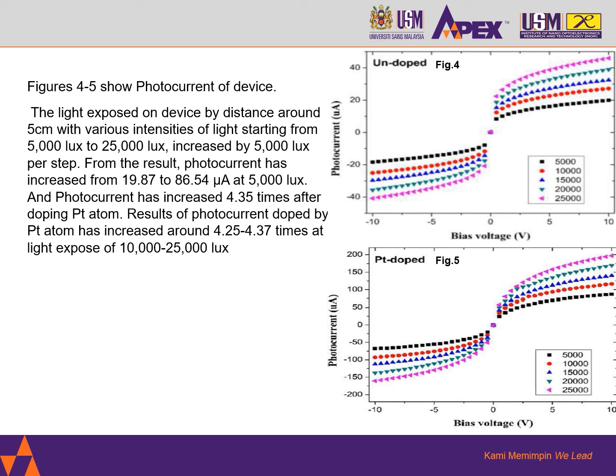The light exposed on device by distance around 5 cm with various intensities of light starting from 5,000 lux to 25,000 lux, increased by 5,000 lux per step. From these results, photocurrent has increased from 19.87 to 86.54 microampere at 5,000 lux, and photocurrent has increased 4.35 times after doping Pt atom.